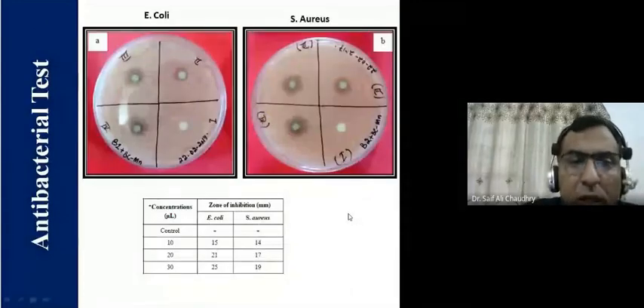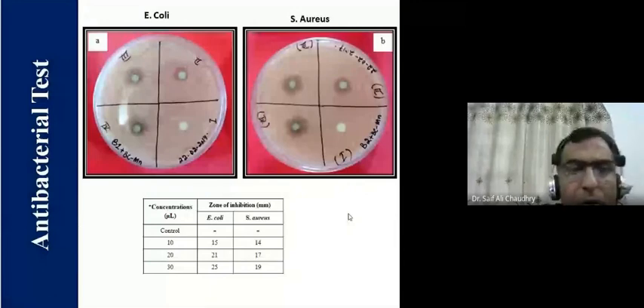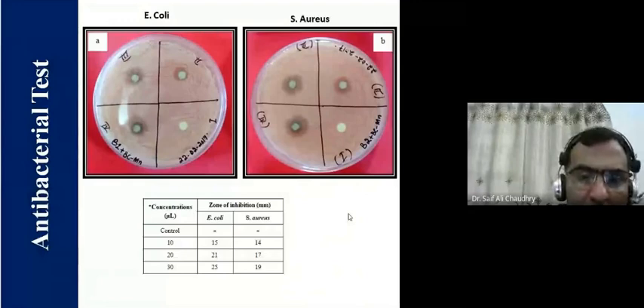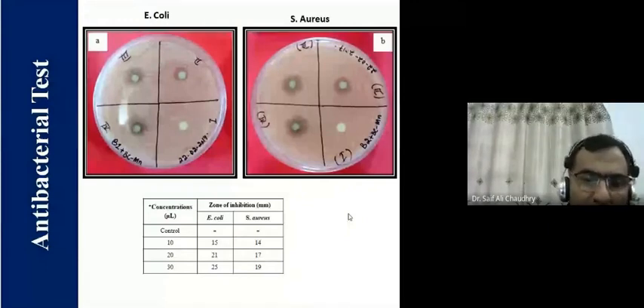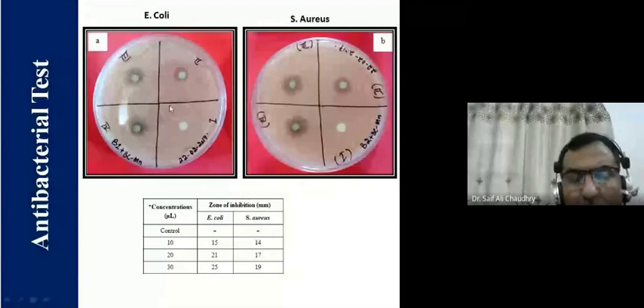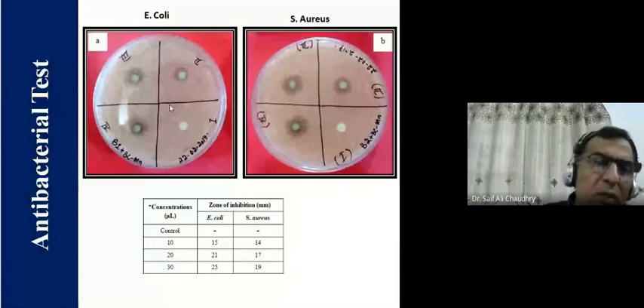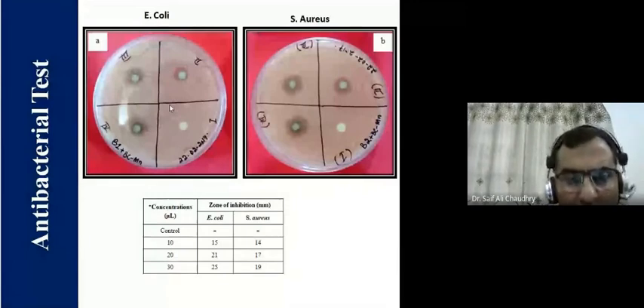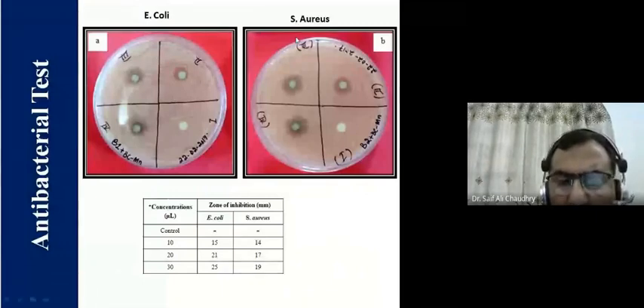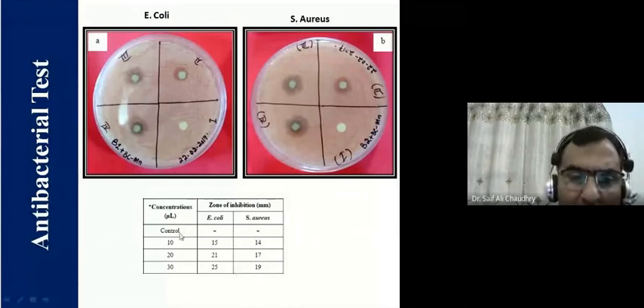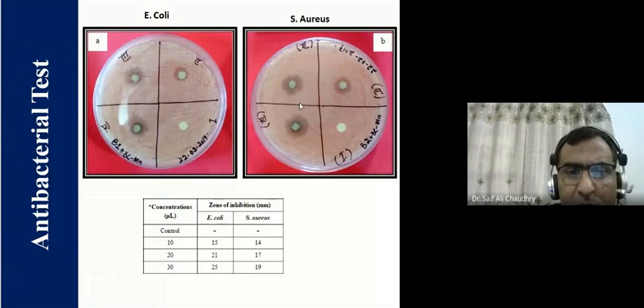Now this is the study we have done on how to control the bacteria E. coli and S. aureus. Both these are positive and negative bacterial strains which we used for our investigations, and we found that the zone of inhibition was maximum for E. coli. Therefore, this MnO2 over BC can be used to control E. coli bacteria in water, or the growth of both bacteria can be controlled in comparison to the control. So our material MnO2 over BC is good in this sense that it can also control the growth of bacteria, both positive and negative.